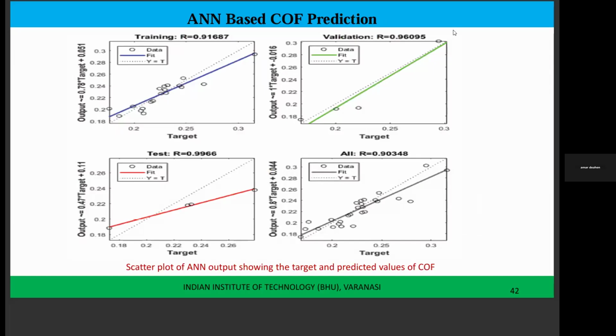When we are doing experiments, they have to be checked, and for the future we need some kind of design data points. For that you have different options: you can go for designing analytically, or numerically, or with something like machine learning and AI. We have information on what the fibers are and what the load, frequency and temperature are, and from that we find the coefficient of friction. So why can't we take those different test parameters as input layers, construct the function, and from that function optimize the coefficient of friction value? Now the model will be there: when you change the input parameters, the fiber percentage, and also the load, frequency and temperature, you can straight away say what the coefficient of friction value should be. No need to do any experiments. Next slide, please.